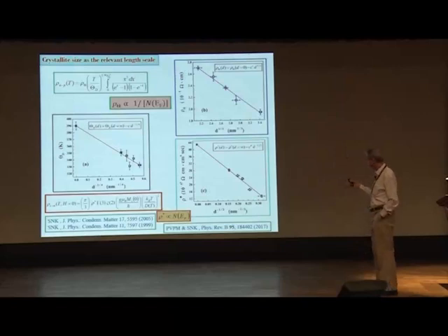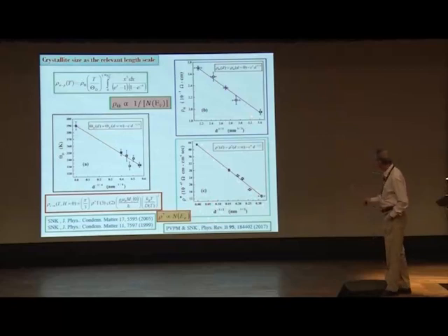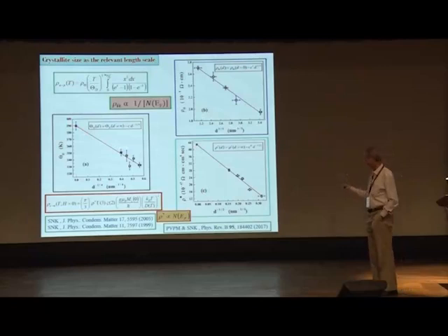That's why they have an inverse relationship, as you can see, where the phonon part is decreasing and this other part is increasing, because I have plotted it as 1 by root d. So this is the bulk value, for example. Similarly, this is the bulk value. So one can understand why you should be seeing this trend, why one should increase and the other decrease. But the very fact that they are going as some powers of the average crystallite size would mean that that is really the controlling length scale.